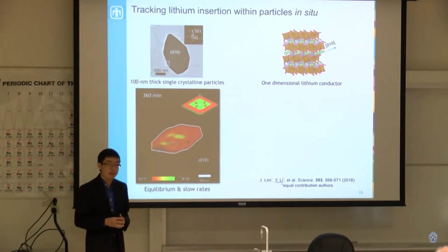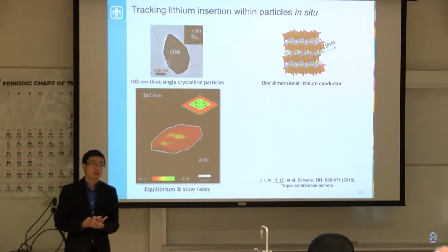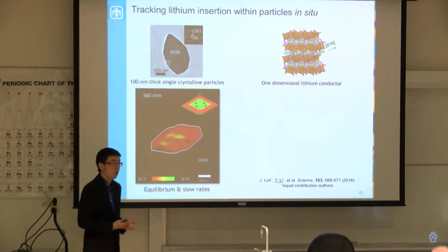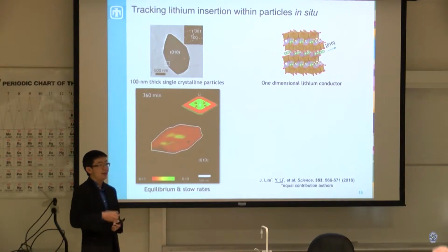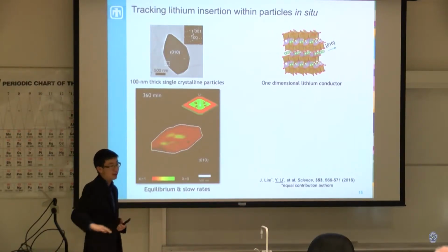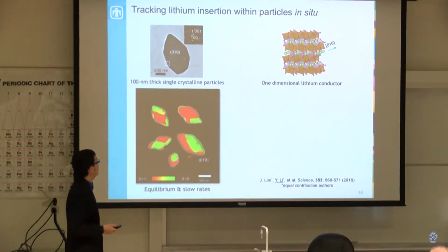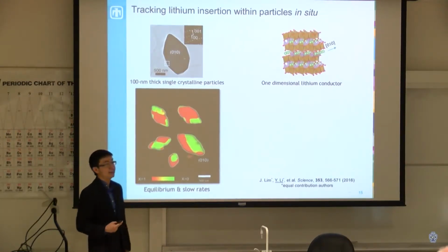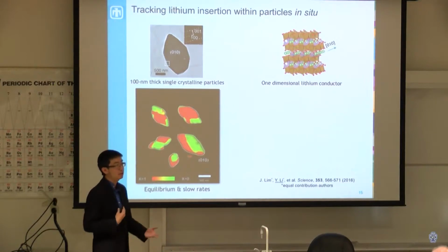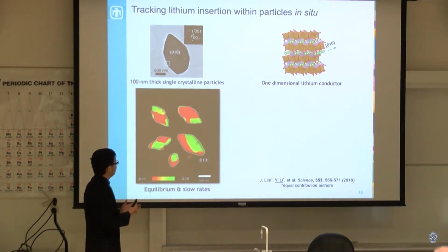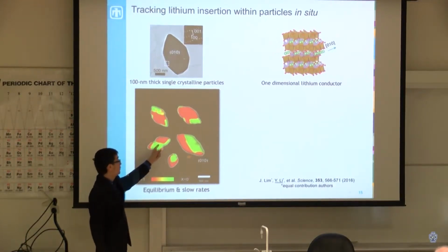We call this phase separation, and that separates into two phases. A very simple example of this might be when you try to mix oil and water, that it will tend to separate into the oil and the water phase. If you add another droplet of water, it will aggregate near the water. So this is also evidence of phase separation. So we do a post-mortem analysis. If we charge up a battery and then we bring it into the light source and try to see what happens, we see these very clear, sharp boundaries between where there's a lot of lithium and where there's very little lithium.